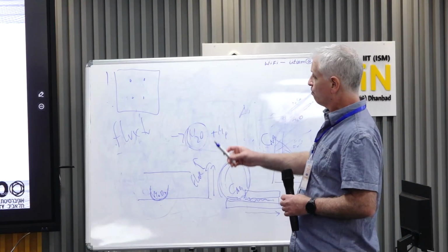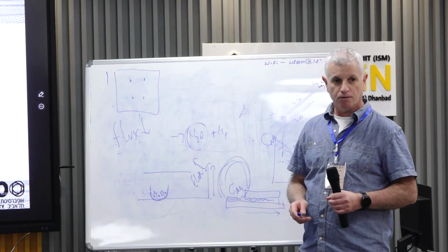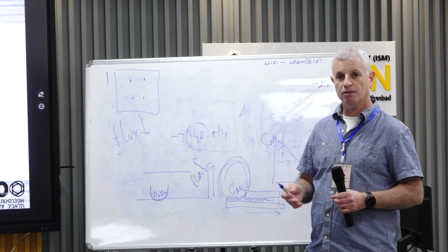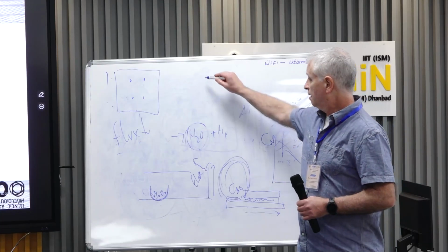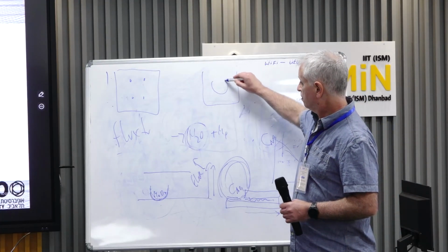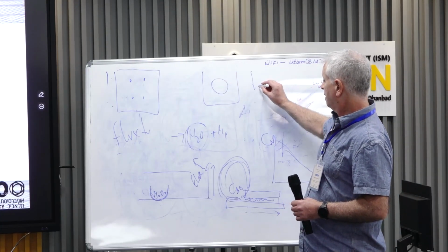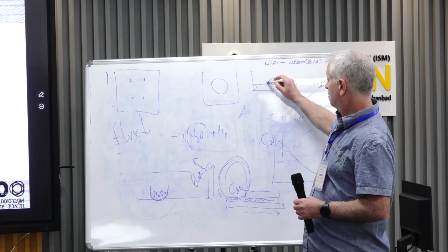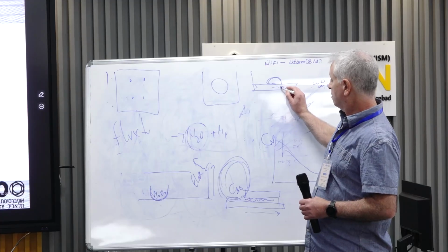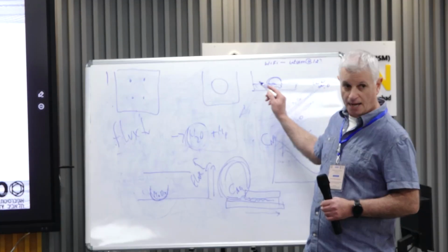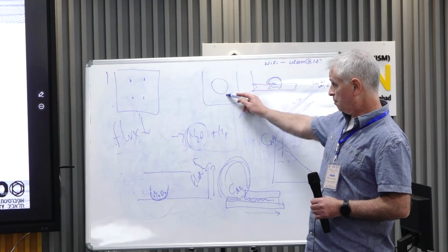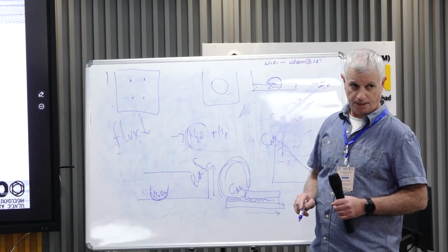Because again, I'll make the analogy to homogeneous nucleation and heteronucleation on top of a substrate. The stable nucleus size that is needed in the heterogeneous case is much smaller than the one needed here, right?